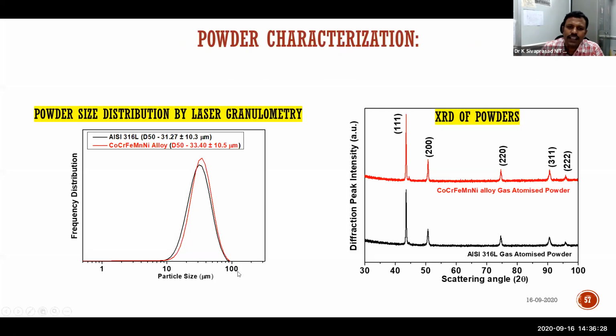So this steel and high entropy alloy powder particle distribution should be the same. So the atomized conditions were also taken like that and collected the 2 sets of powders. And the powder XRD was done. It is shown clearly that these powders are showing single phase FCC again. XRD will tell you whether it is FCC phase, single phase, or multi phase like that.